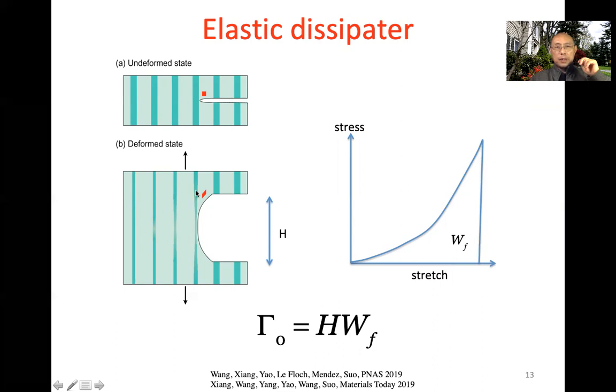So the point is, because there's enormous blunting, you deconcentrate stress, spreading stress over a long distance of the fiber. In our case, H is on the order of millimeter to centimeter. Then, of course, when this fiber breaks, you dissipate energy over a long segment of fiber, H. So that's why your energy is very high.